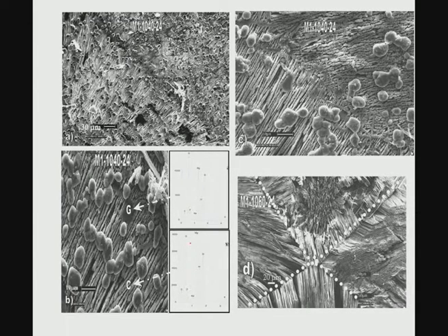Interestingly, when these materials were ceramized for 24 hours at 1060 degrees Celsius, I describe this morphology as envelope-like crystals, like a postal envelope. These crystals essentially have 4 different domains, and in each domain the straw-like crystals are oriented in a particular orientation, and this orientation differs. There is a clear transition at the domain boundary, which is shown here in the dotted line.